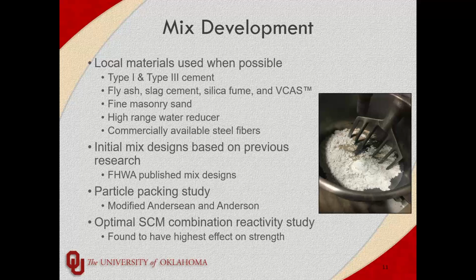We figured that'd be a good starting point, and maybe if we got lucky, then the materials we were using would produce similar results, and we would only have to do some fine tweaking. But unfortunately, it didn't work that way. We found that a lot of the mix designs that we mimicked didn't actually get the same properties as the FHWA had published, and figuring there could be any number of reasons, we decided to go ahead and branch out and look around using different materials and different mix designs and trying to find out what that best combination would be.